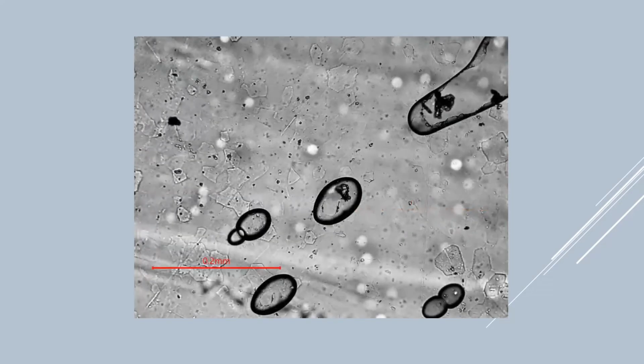Here's some more bubbles. We get a lot of bubbles on in-situ replicas, and clients seem to get quite annoyed at them. But when you apply the acetone to the cellulose acetate, sometimes you apply too much, or maybe you haven't let it dry enough, and you have to reach way over to apply it to the surface that you polished. It's not right in front of you, and so sometimes you do get bubbles on these surfaces. The only thing you can do is take another replica if there's that many of them, or maybe just move to another area on that slide where we don't have bubbles.